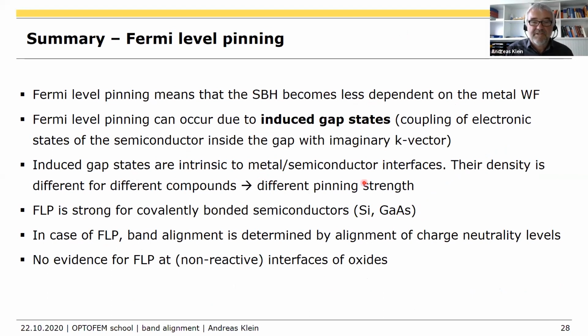So not every material has a high concentration of induced gap states, so not every material gives us an intrinsic pinning. But particularly the covalently bonded semiconductors silicon and gallium arsenide show strong Fermi level pinning. And in this case, the band alignment is determined by the charge neutrality levels. And finally, for the oxides, there should not be much pinning. Okay.